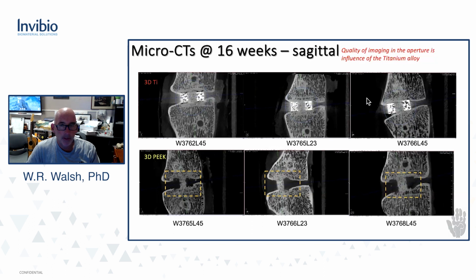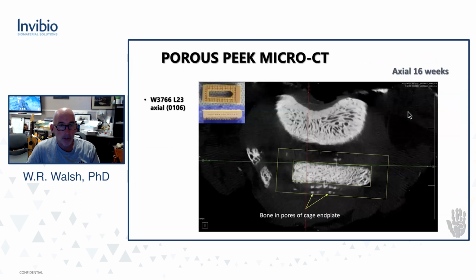Again, the fusions have progressed, but again, what's happening inside, it's easy to tell with the PEEK. It's more difficult to assess the aperture as well, but it's really hard to tell what's happening inside the porous domains. So with micro CTs, we have the opportunity to cut them in different orientations. What we did in this slice was cut the PEEK right at the top. And so this is looking at an axial view right at the top. And you can see just in the top of the cage, there's bone integrating into the porous domains of the cage. So we've got kind of spot welding happening, which is a nice sign of integration and stability.